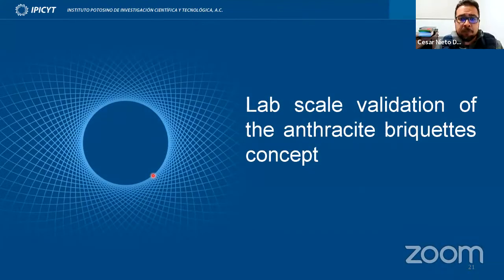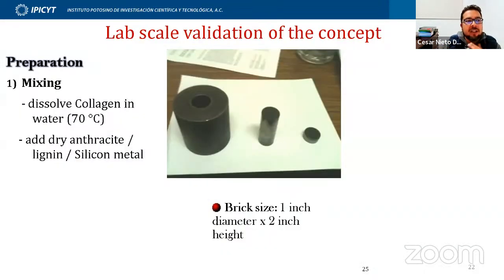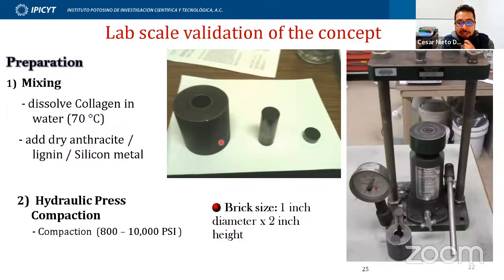But anyway, now I am going to show you a little bit about the lab scale validation that we did to prove the concept of using these three binders to bind the anthracite fines together. What we did is make a mixture of the dry components, which is the anthracite, lignin, and silicon metal, and bind it together with collagen dissolved in water, and we use this die to produce a brick.